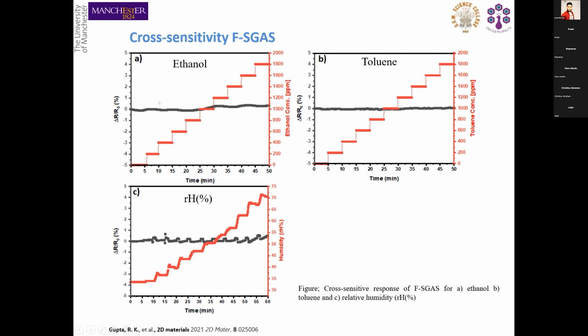We see that we do not see any change in the sensor response when you increase the ethanol concentration from a few ppm to around 1800 ppm. The sensor doesn't respond. Similar with the toluene, and there are small jumps with the humidity, but it doesn't show as much as the change in concentration of the formaldehyde. So that proves that the sensor is selective to formaldehyde molecules, selectively picking up the formaldehyde from the diffusion chamber, and it was insensitive to any other gases.